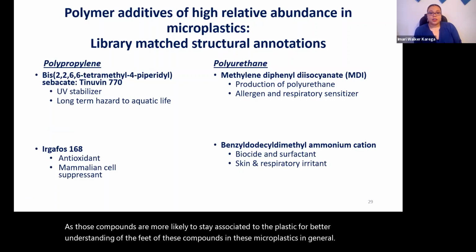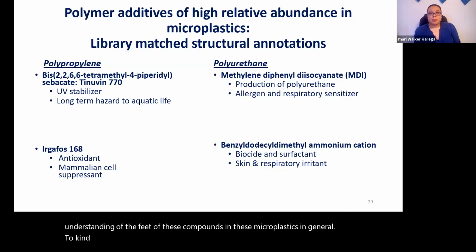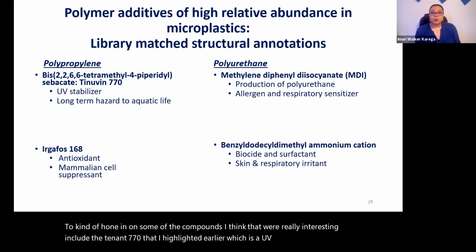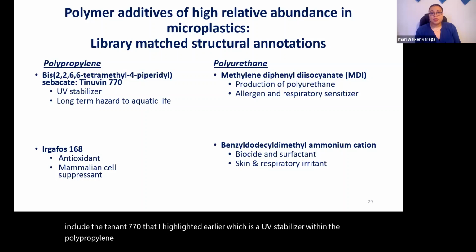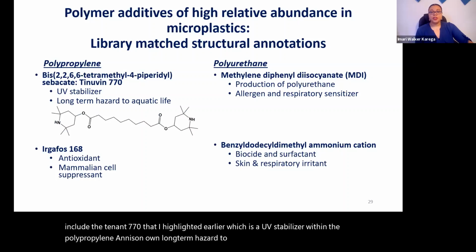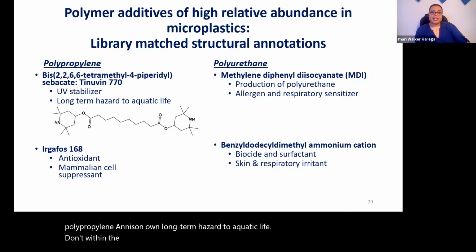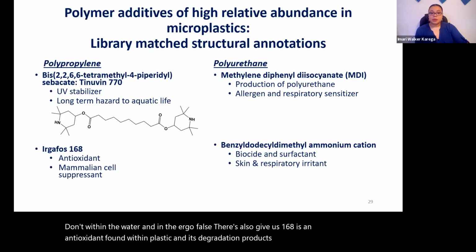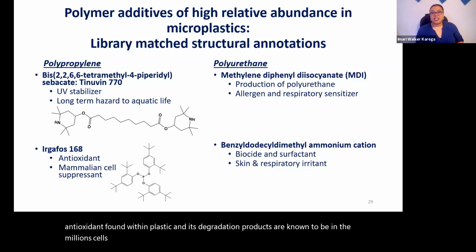To highlight some of the compounds I think were really interesting: the Tinuvin 770, which I mentioned earlier, is a UV stabilizer within the polypropylene and a known long-term hazard to aquatic life in the water. There's also Irgafos 168, an antioxidant found within plastic whose degradation products are known mammalian cell suppressants, and that was found to stay associated with the plastic, so it might be good to look for in the sediment.